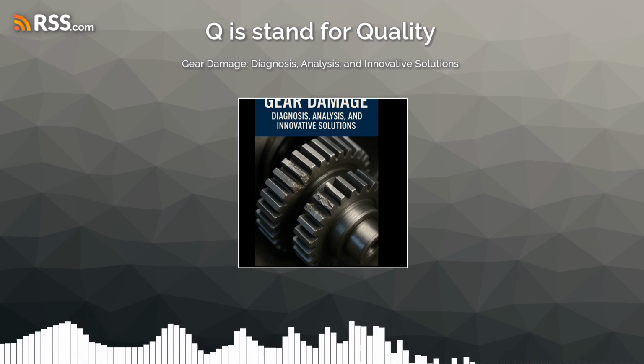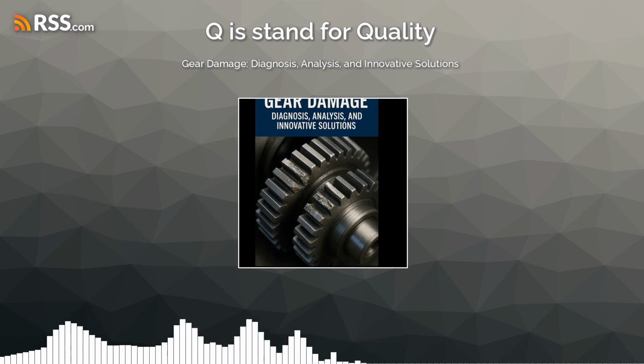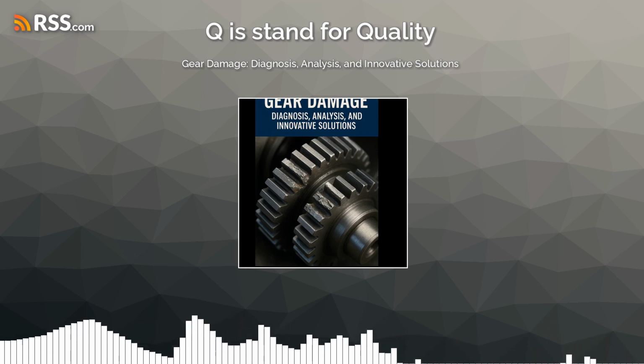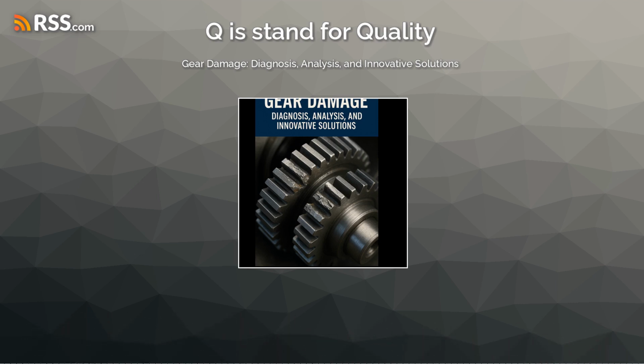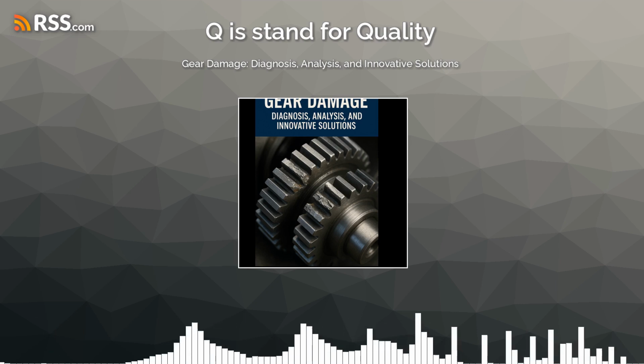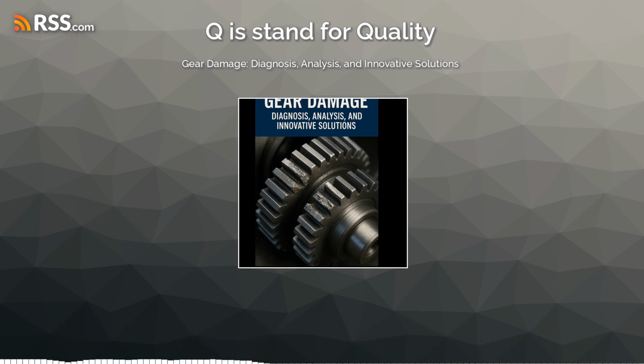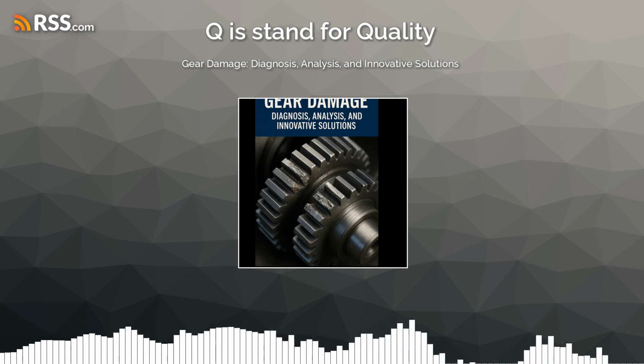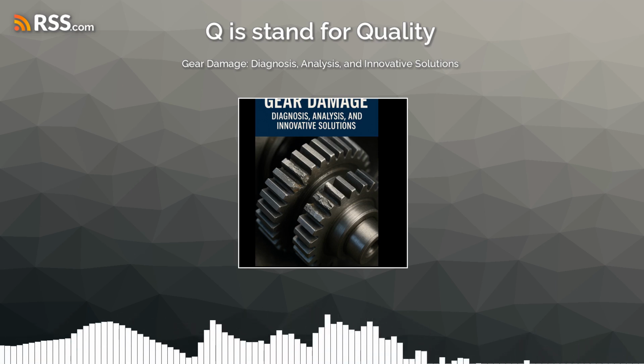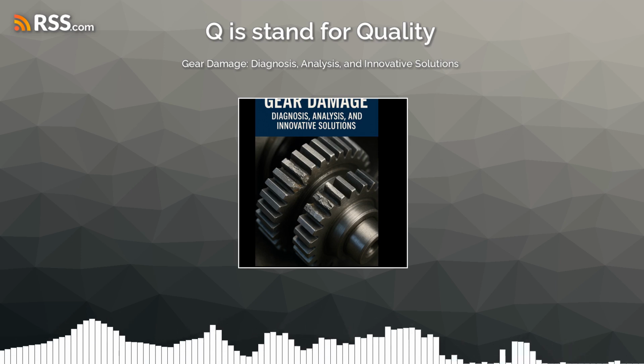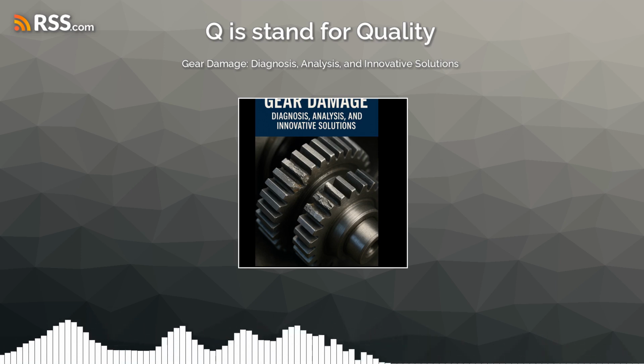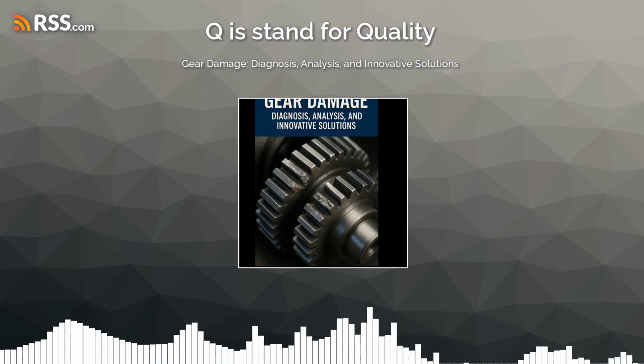They also generally have lower thermal conductivity. They trap heat easily. And higher thermal expansion, they change size more with temperature, which can cause misalignment. Any other downsides? Some polymers, like polyamide, absorb moisture. This makes them swell and can reduce their strength. So you really have to pick the right polymer for the specific operating environment, temperature, humidity, load. Get it wrong, and failure can be rapid.